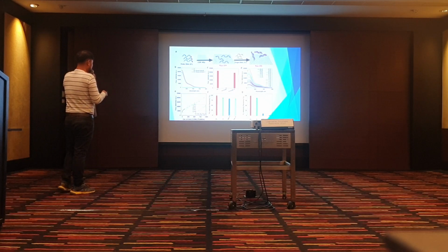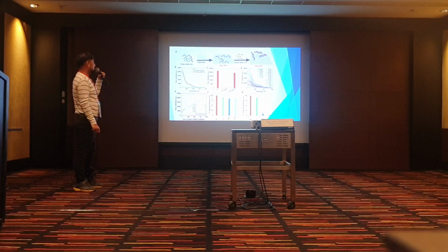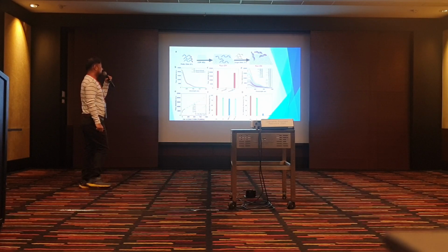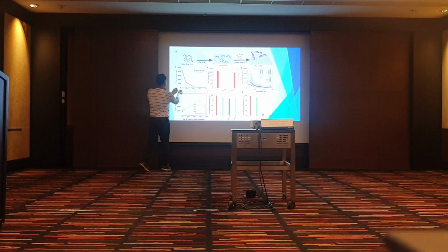So here we give some example. You can see P1 is our particular probe that we are taking with the fluorescence material. When we put our COF with that material, fluorescence goes down. There is quenching, not possible 100%, near 99% quenching.